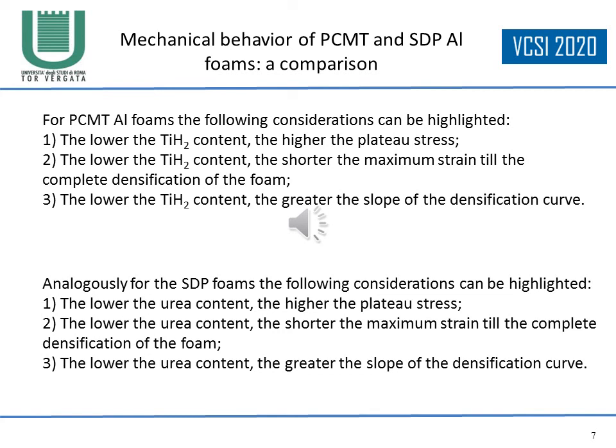Analogously for SDP foams, the following considerations can be highlighted: the lower the urea content, the higher the plateau stress; the lower the urea content, the shorter the maximum strain until complete densification of the foam; and the lower the urea content, the greater the slope of the densification curve.